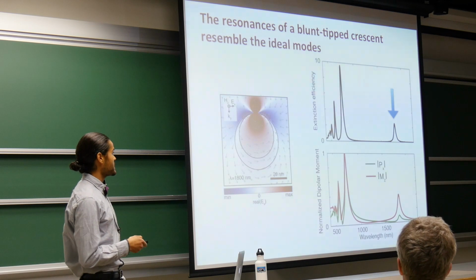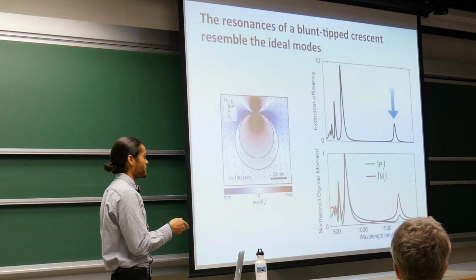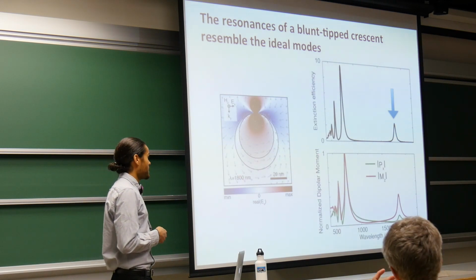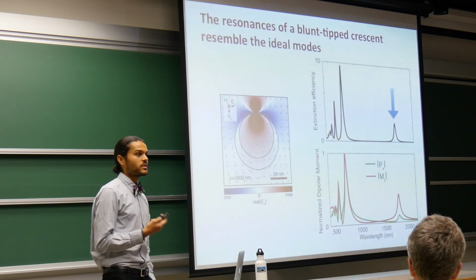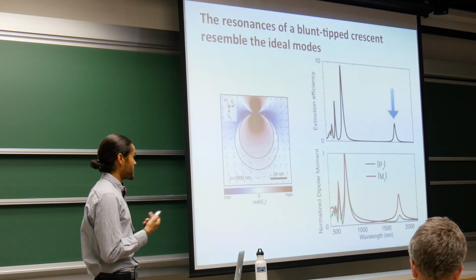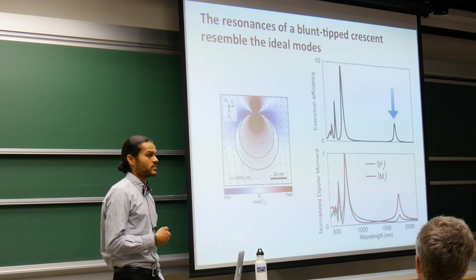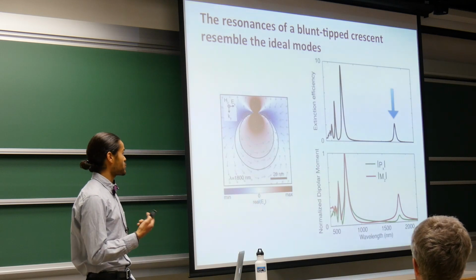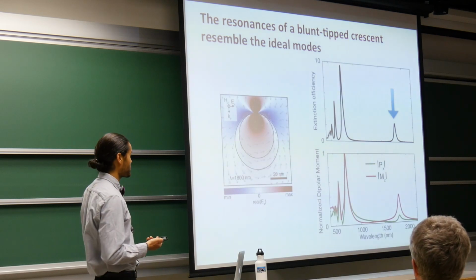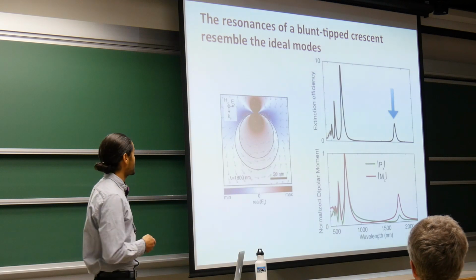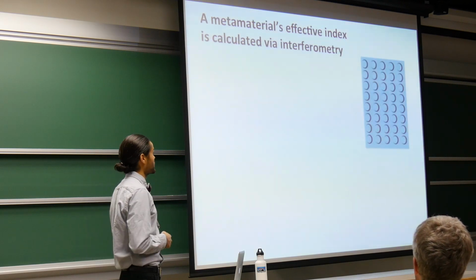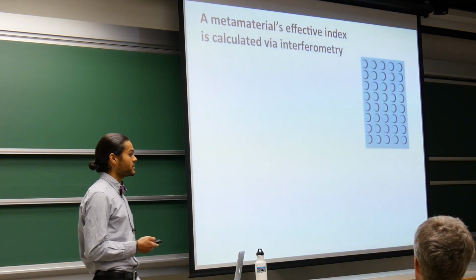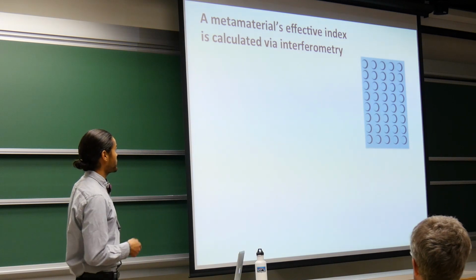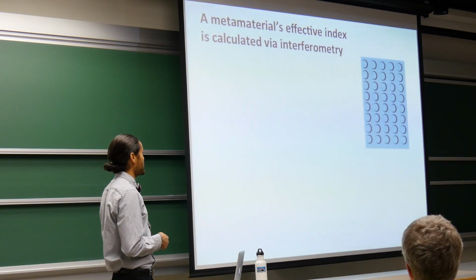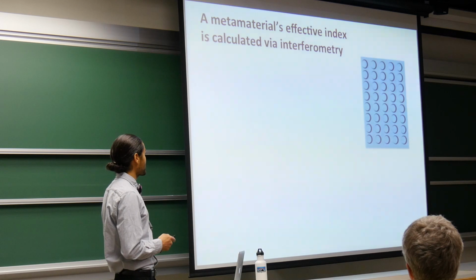And when we do this, we see that each of these modes throughout visible and near-infrared frequencies is composed of both electric and magnetic character. So in essence, we can use this meta-atom in a metamaterial to control both the electric permittivity and the magnetic permeability of our material. So the only step left is to actually make the metamaterial, in theory, of course, where we put the crescents next to each other and embed the crescents into a dielectric slab.